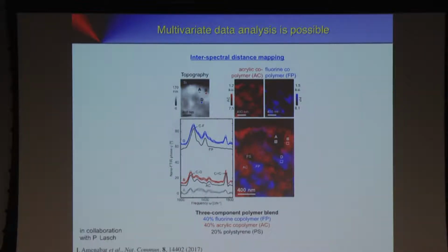We can overlap these areas, and then we have the blue areas indicating the FP, the red areas, and we have these black areas here. We couldn't find any agreement, and the reason is that we have here very likely the polystyrene, and for the polystyrene, we didn't get actually a good spectrum because the vibrational signature of polystyrene is rather weak. So that's why these areas are black here. But in the end, it shows that without any significant data processing, we can do standard multivariate data analysis and get these compositional maps here.